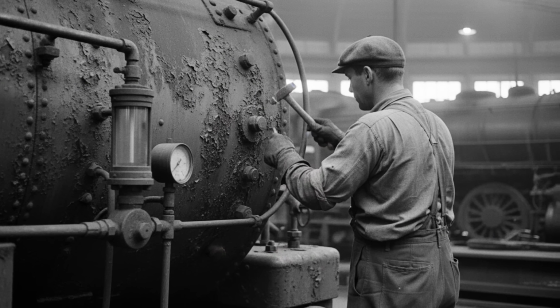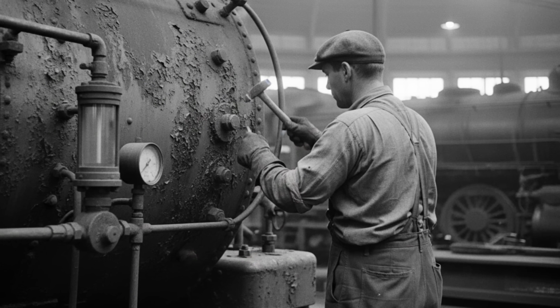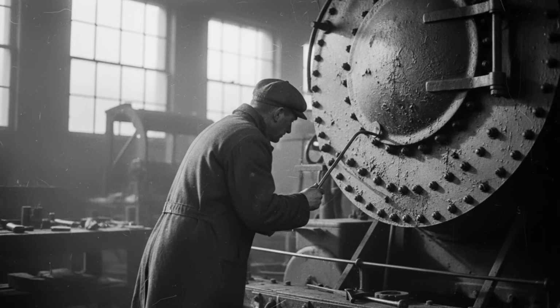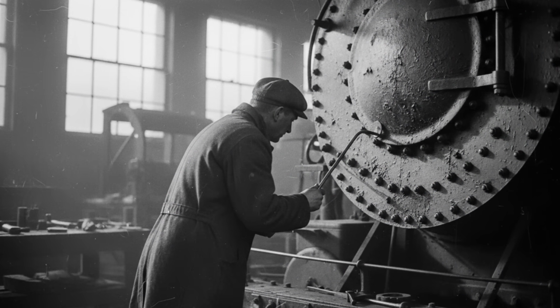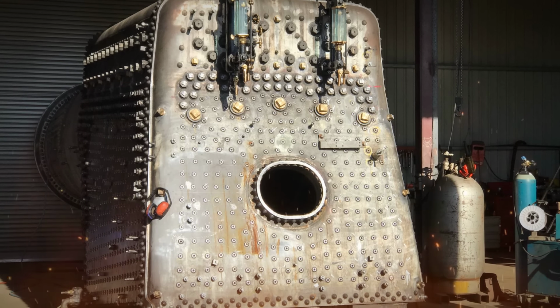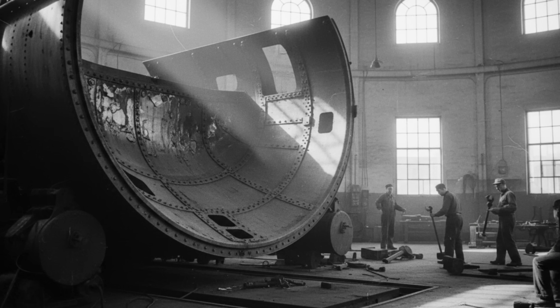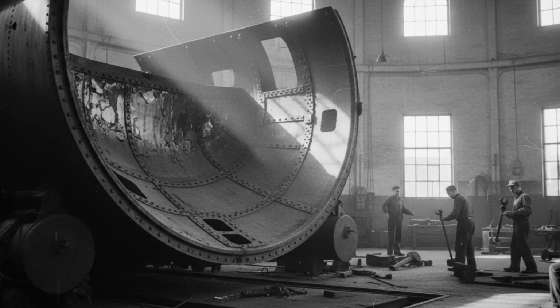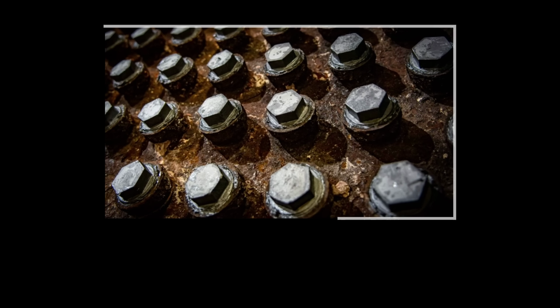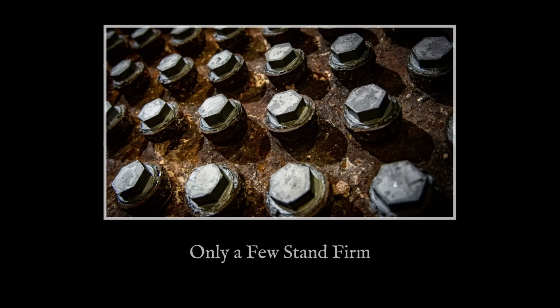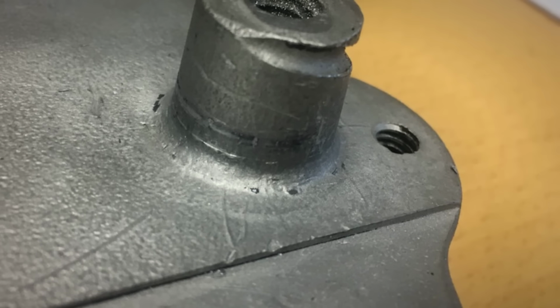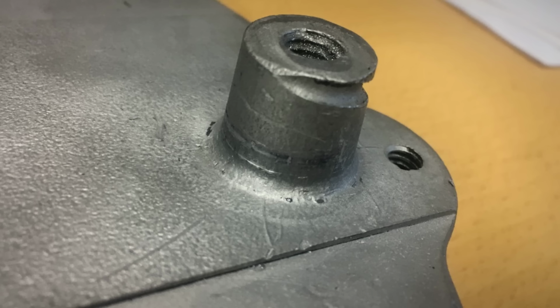Inspectors tap each bolt with a hammer, listening for a dead ring that betrays a fracture, but not every failure sings before it snaps. When the crown sheet overheats, the steel around the stays softens, and the once rigid grid begins to sag. The load concentrates on a handful of survivors. One by one, they shear off, leaving the plate unsupported.